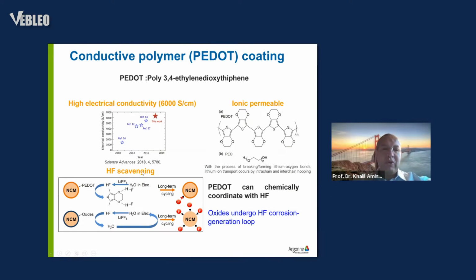This is important because the salt in the electrolyte is LiPF6, which can hydrolyze and form HF, and HF can actually dissolve some of the transition metal oxide from the cathode, leading to capacity fade. So by scavenging the HF, we can actually prevent this type of phenomenon from happening.